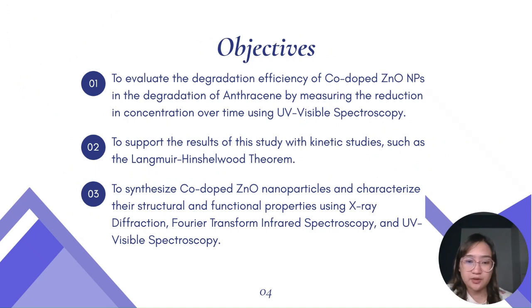The following are the objectives of this study. First is to evaluate the degradation efficiency of cobalt-doped zinc oxide nanoparticles in the degradation of anthracene by measuring the reduction in concentration over time using UV-visible spectroscopy. Second is to support the results of this study with kinetic studies such as the Langmuir-Hinshelwood model. Third is to synthesize cobalt-doped zinc oxide nanoparticles and characterize their structural and functional properties using X-ray diffraction, Fourier transform infrared spectroscopy, and UV-visible spectroscopy.